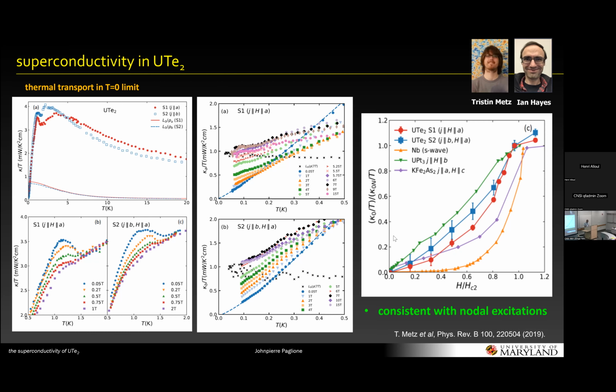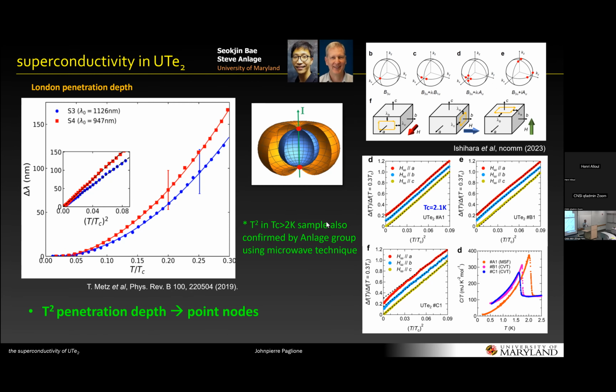Not fully gapped. Okay, so we saw an NMR that may be consistent with a gapped superconductor, maybe not, but it's been triplet. Thermal conductivity that suggests there's nodes. The penetration depth that's been measured by my colleague Steve Anlage in Maryland and also by the Shibauchi group, it's fairly consistent in that they see a quadratic temperature dependence. And the important thing is that they see it in all three directions, also seen by Steve as well. And so that suggests that you have these nodal-like excitations in all directions, or at least some component.